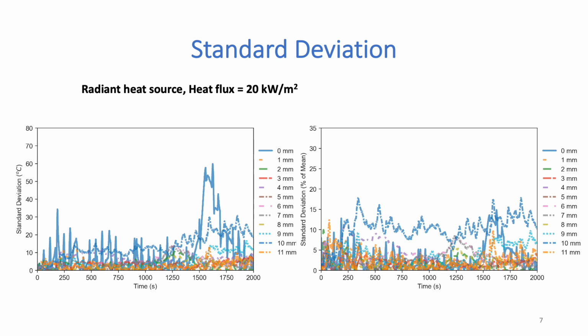We also calculated, to try to understand, the experimental uncertainties. So we looked at standard deviation, the actual values of standard deviation, and the standard deviation as a percentage of the mean temperatures. We found significant deviations because of local irregularities in the gypsum board and experimental and measurement uncertainties, up to 15% deviation for lower heat fluxes, and that even increases further when we did experiments with turbulent flames and high heat fluxes.